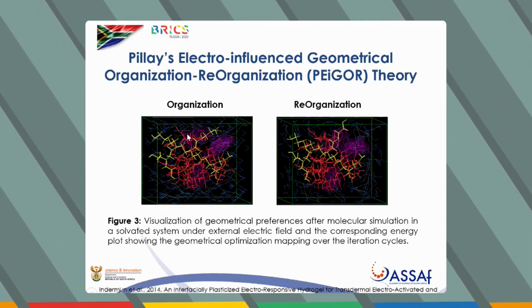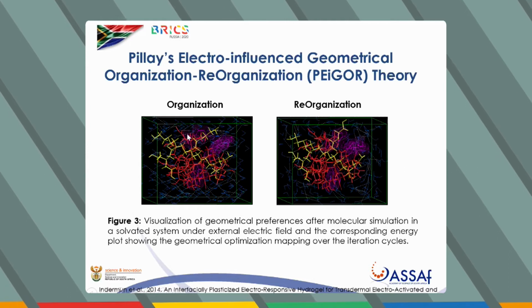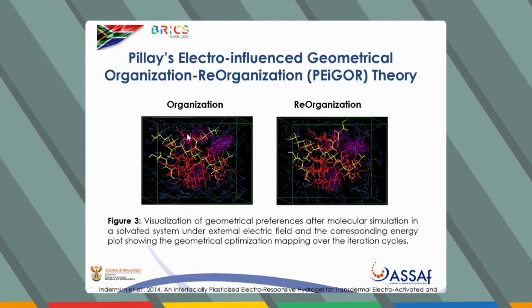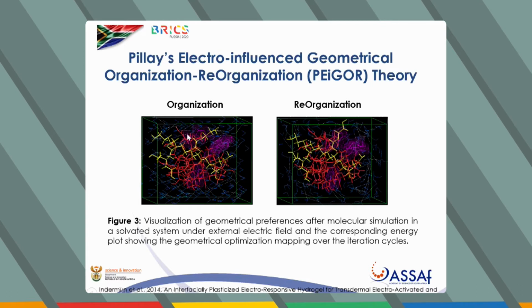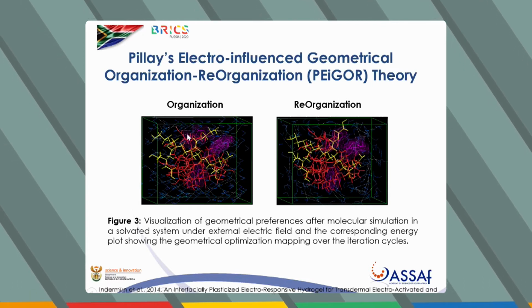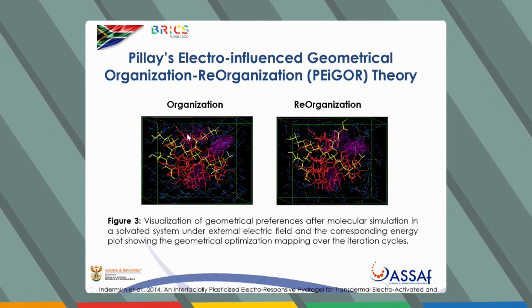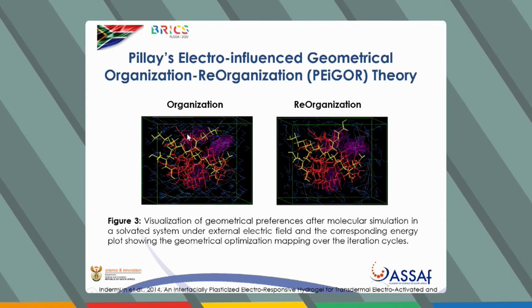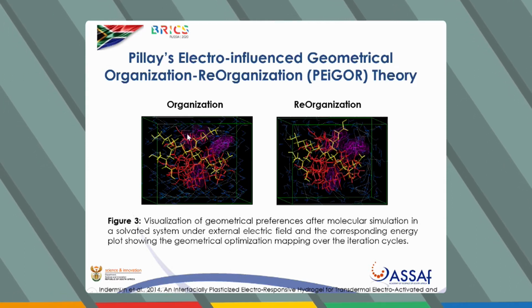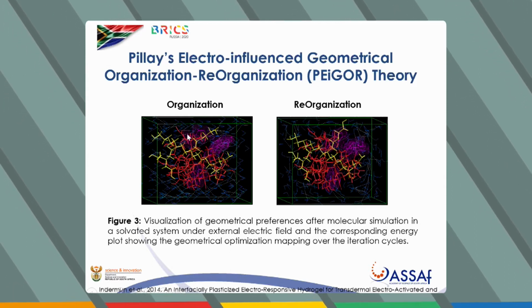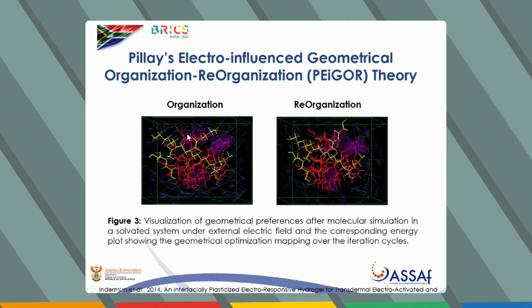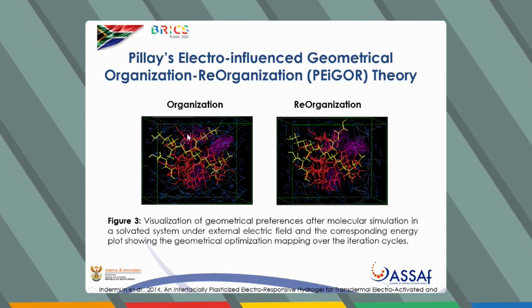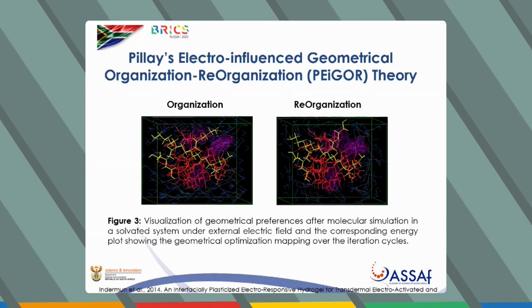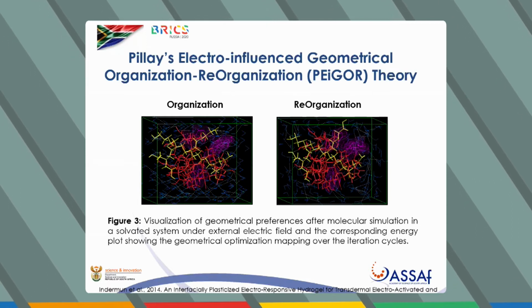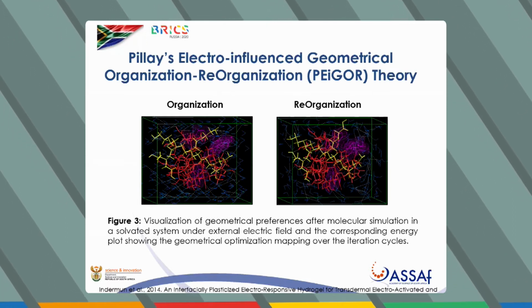Of drug release. Whereas in the reorganization phase, the polymeric chains reorganize with respect to the surrounding solvent and polymer molecules via local orientational correlations. As a result, there's a change in the reaction coordinates. This results in solvent relaxation. Then we have a decrease in static energy, which results in an increase in polymeric networking. And then we have retention of the drug in the network.